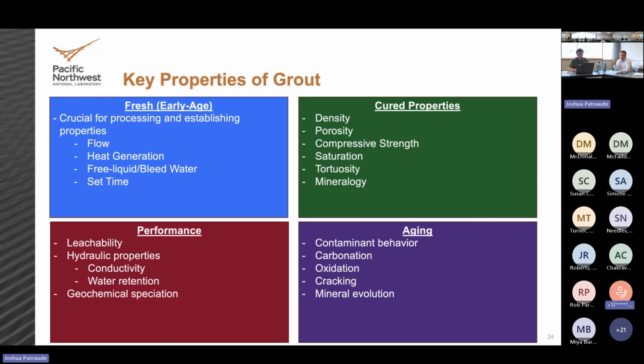So the key fresh properties that we concern ourselves with are flowability, which is just when we do that initial mixture and it's in its slurry state, how easy does it run? How viscous is it? In cement concrete, you would use what's known as a slump test, where you take a big cone, fill it with your material, pull it up, and it makes a hat. And however far that material slumps down gives you a sense of flow.